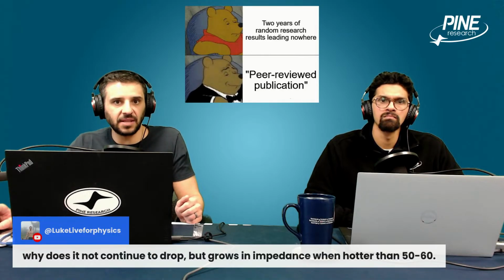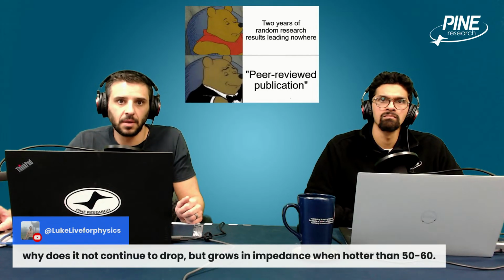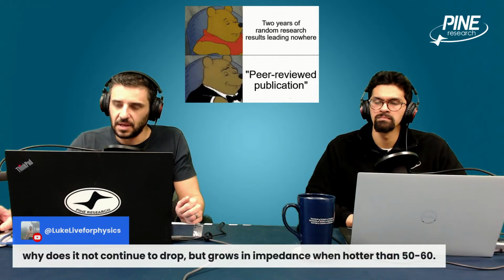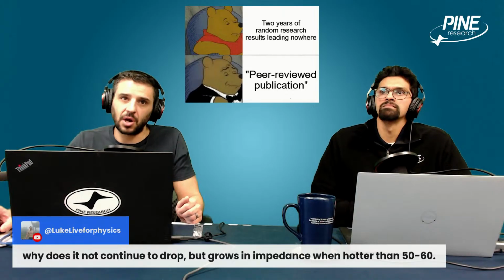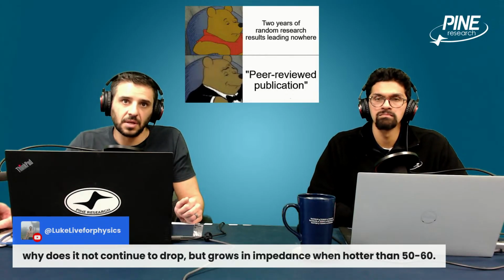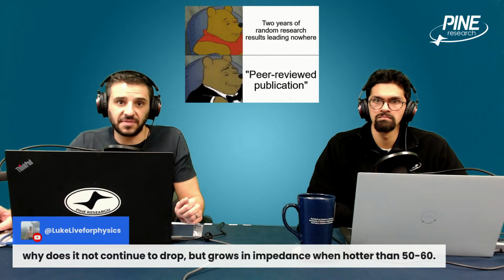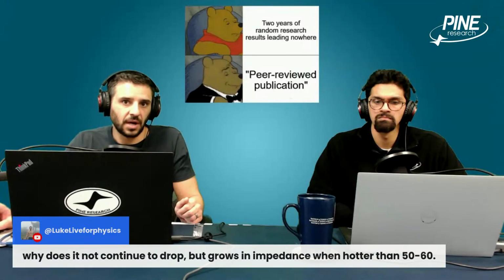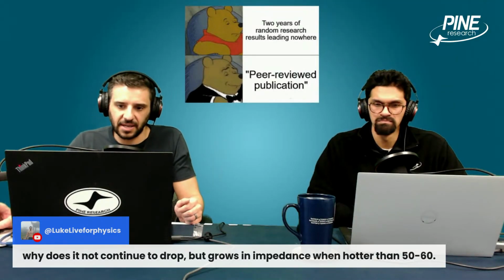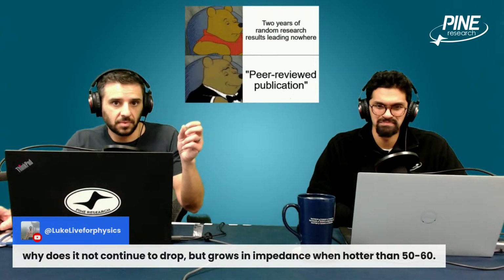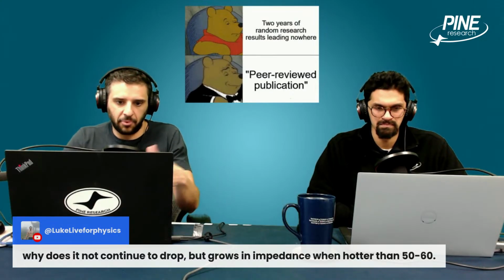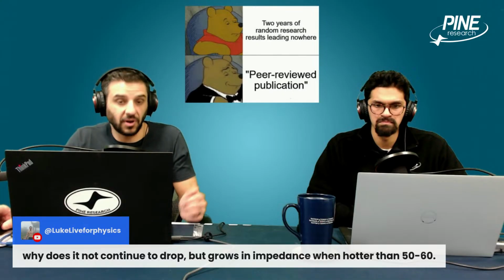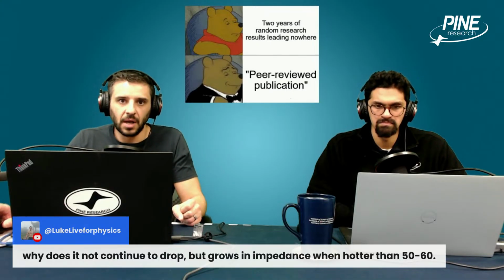In your case, if you're finding that these things are reversible, it's probably that, if the SEI collapses, it can reform. If the elevated temperature causes, for instance, agglomeration of material that reduces the number of active sites at either the anode or the cathode or both, the impedance will go up because there's fewer active sites available. That's like an increase in the entropy, like you talked about, right? It's going to make it more difficult to do the electrochemistry at either or both electrodes. But as you lower the temperature back down, it breaks up. It reverses itself. It goes back to what it was before.